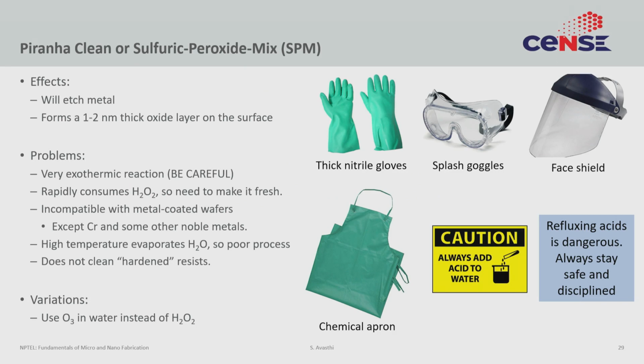It is incompatible with metal coated wafers. We have already discussed that. There are certain exceptions like chromium and other noble metals which tend to not get reactive with sulfuric acid. So in some of those cases you can use this clean. The high temperature evaporates water, so the concentration of sulfuric acid actually changes in the system. So the process control is not very good.